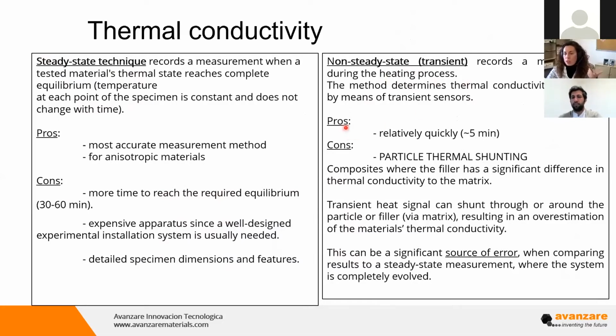So this is a quick way to measure the thermal conductivity, but as we will see after, there are some effects in the case where the filler is of higher conductivity than the matrix, like in the case of graphene, where particle thermal shunting can occur, and it can be a source of error because it translates into an overestimation of the thermal conductivity. In the case of steady state techniques, it usually records the thermal conductivity during the equilibrium. So it's considered the most accurate method. However, it's more time consuming.